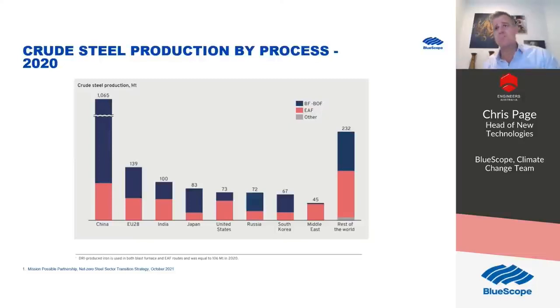Now you can see there's a very small area of grey, which is other, and that basically represents the DRI processes that are in the world. So as you can see, mostly steel, about 70% of it is made via the blast furnace BOF, 25% is made through the EAF process exclusively, and then about the last 5% is made through the DRI process.